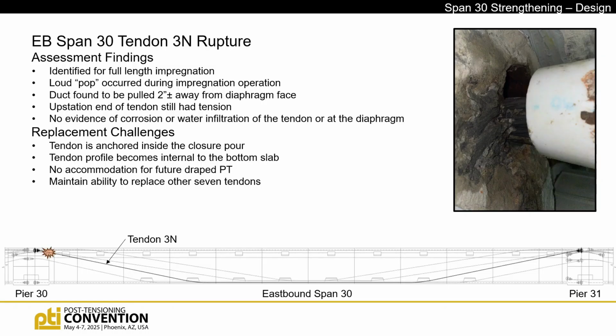unfortunately, we did have an issue in the impregnation process. While impregnating, it was close to one of the last tendons on the project, if I remember right. The team told me they heard a loud pop. It sounded like a gunshot going off inside the bridge. A cannon. A cannon? Okay. Didn't initially see anything. Obviously stopped impregnation operations, but then went for the weekend. It took a couple days, a couple thermal cycles, came back and found what you see here, which is the duct, which is pulled about 2 inches away from the diaphragm face.